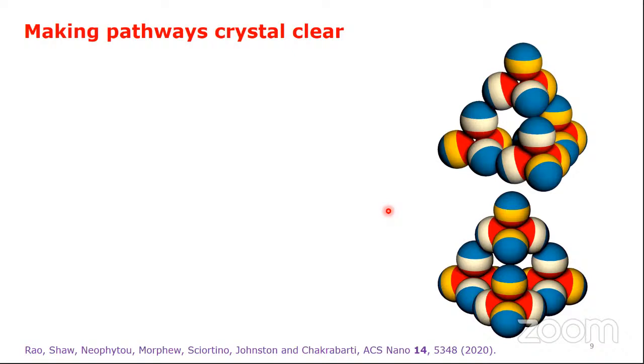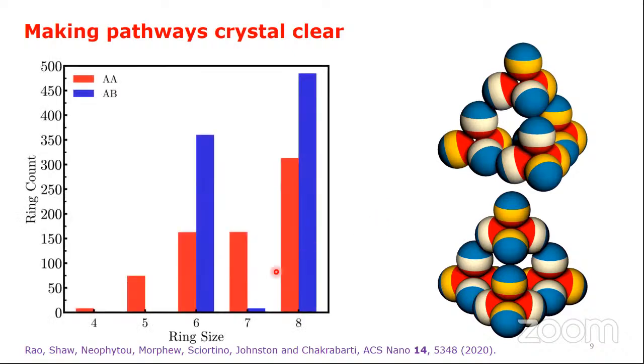The answer lies in the ring statistics. As shown here, the perfect crystal has 6 and 8-membered rings. The ring statistics show that the two-stage self-assembly via tetrahedra suppresses the formation of 5 and 7-membered rings, which when present prohibit the emergence of long-range order.